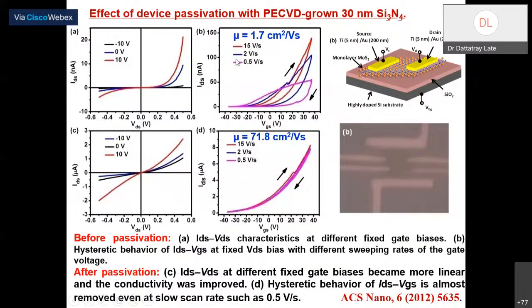You can see the mobility measurement before passivation is 1.7 centimeters square per volt second. After coating, it is 71.8 centimeters square per volt second. Because now we have improved contact, then because the device is also annealed and a lot of functionalities have been removed, this gives better characteristics after coating with silicon nitride.